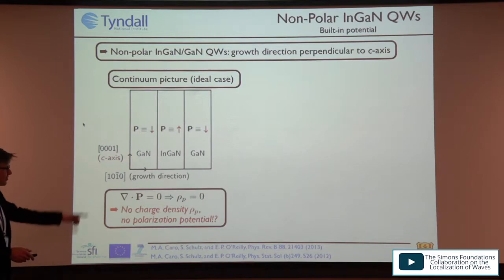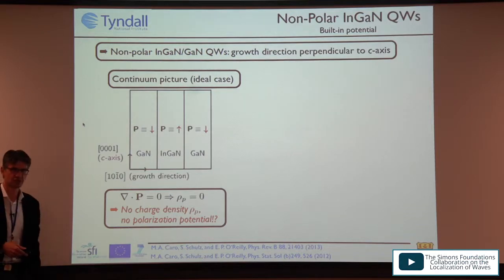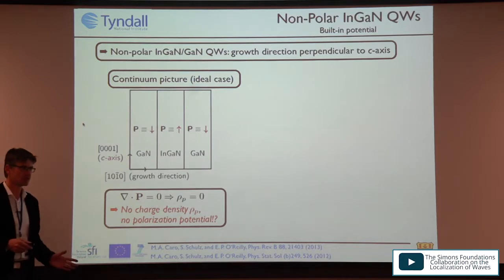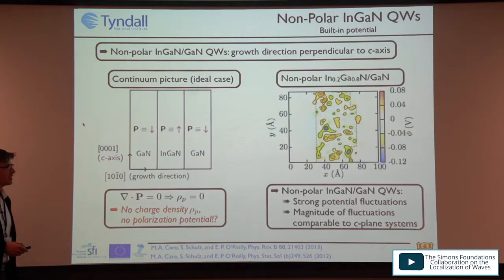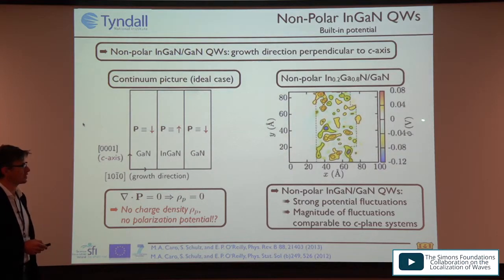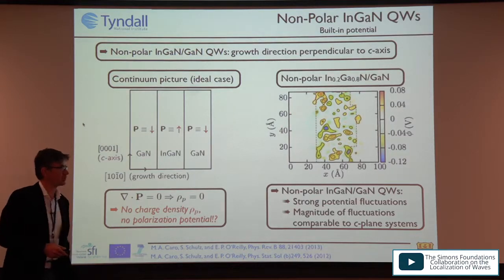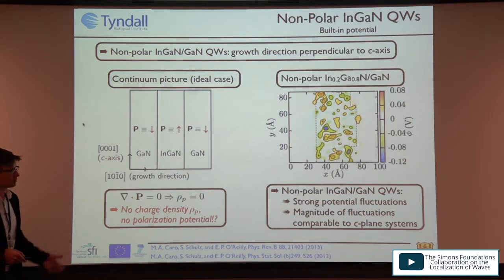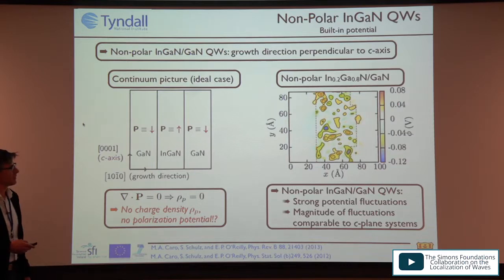Regarding the magnitude: this is in volts, and can be quite a significant local effect — several kT. Regarding the absolute polarization needed for the discontinuity between GaN and InGaN: the macroscopic or clamped-ion contribution provides this, using DFT calculations similar to those of Bernardini and Fiorentini. For moderate indium contents in the lower range, the standard approach gives compensating errors that are usually acceptable, though inhomogeneities could matter more. The absolute value of the clamped-ion contribution may shift, but the fluctuations sit on top of this.